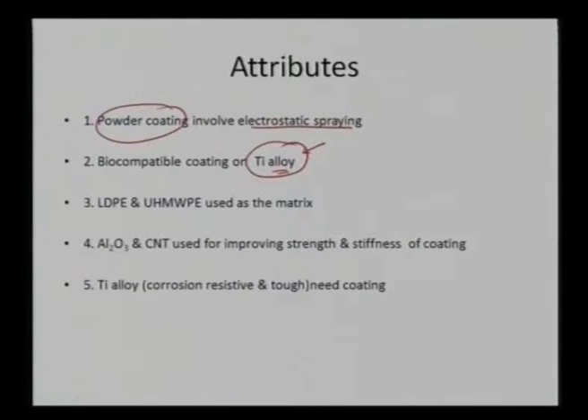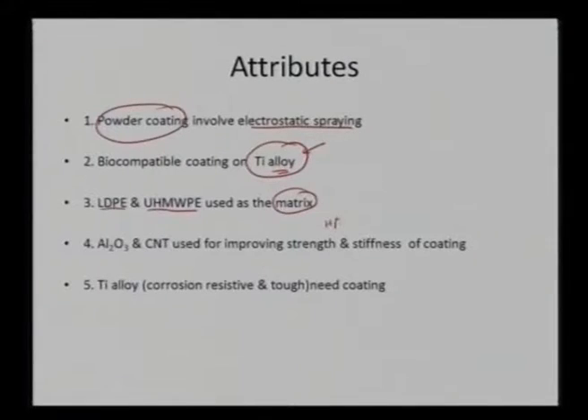Once we have that, we can utilize either low density polyethylene or ultra high molecular weight polyethylene as the main component of the coating. So we are going to deposit a coating which is rich in polyethylene, and we can make that a major constituent of the coating. Because these coatings are very soft in nature, we also want to increase their wear resistance or tribological properties. For that, we can introduce hydroxyapatite, or ceramics such as aluminum oxide, or we can also incorporate carbon nanotubes for improving the strength as well as stiffness. Once we have much superior mechanical properties, automatically we can expect that the wear or tribological properties will also be enhanced with the reinforcement.